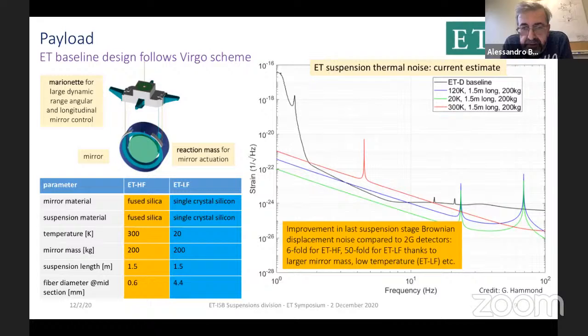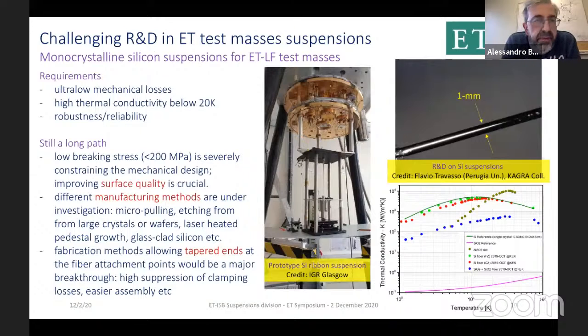So what we do expect, if you look at this graph, is a 6-fold improvement in displacement noise at room temperature, and up to 50-fold improvement at low temperature for the low frequency detectors. For the payload development, there is a lot of R&D to be done. And here I would just highlight two critical aspects that need to be addressed in the relatively short term.